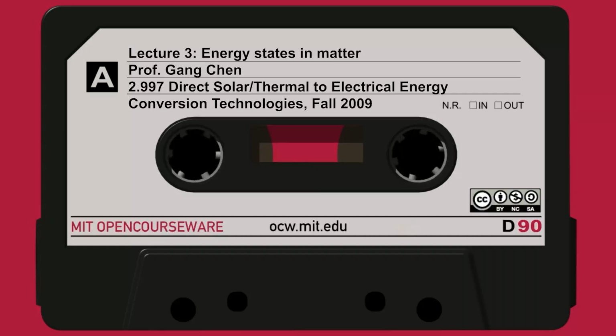And in metal, the next state just close to this point is very close. The energy difference is very small, right? So the thermal energy is large enough to allow them to go to the next state. So only when your electrons fill the band with empty states left, it's a conductor. It's metal. That's metal. Okay. And what happens if my number of electrons fills to here?